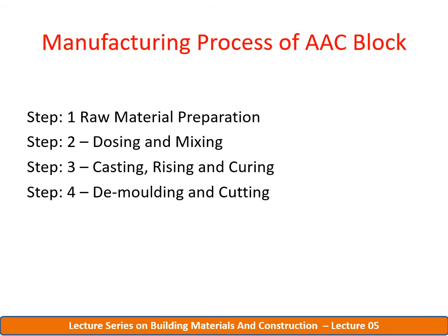After the above raw material mixed is ready to pour into the mold, these blocks can be of various size depending upon installed capacity, like 4.2 by 1.2 by 0.65 meter in size. Before pouring mold with the mix, molds are coated with the thin layer of oil in order to ensure that green cake does not stick to the mold.